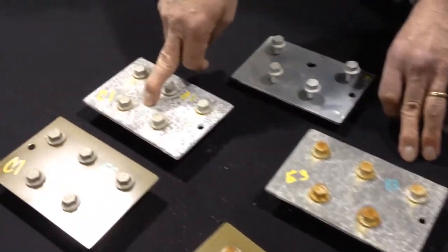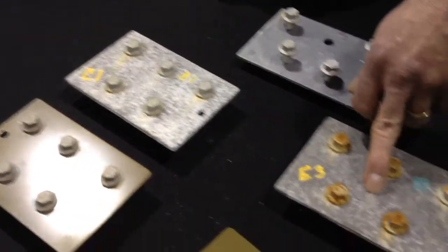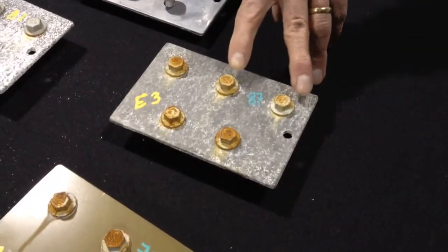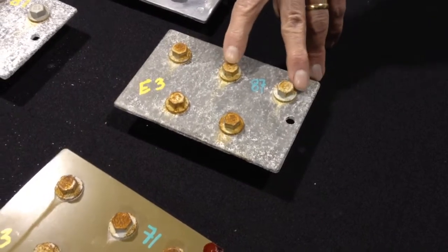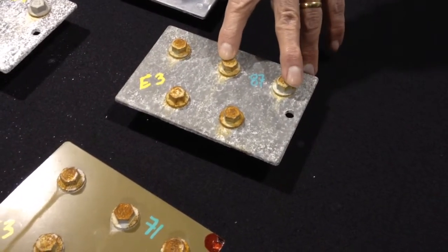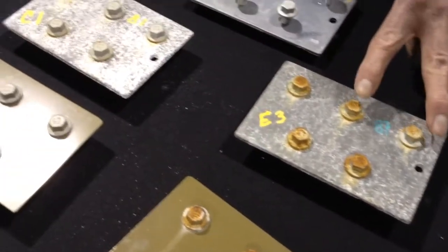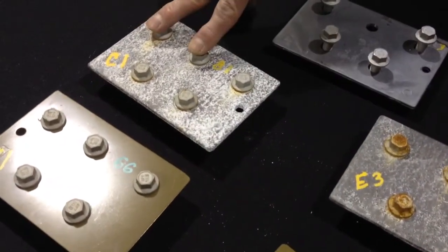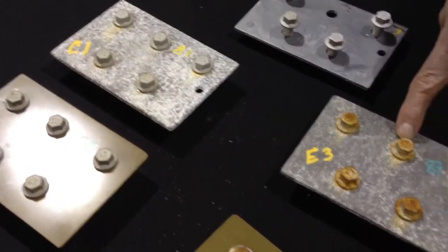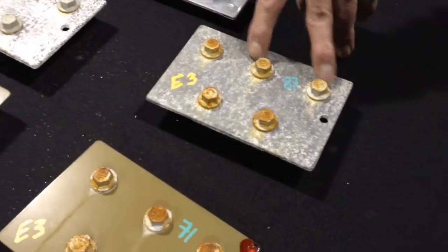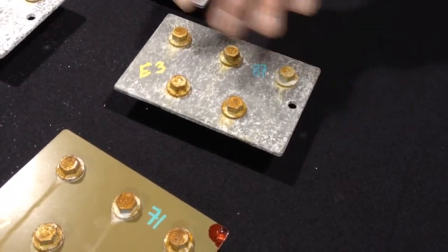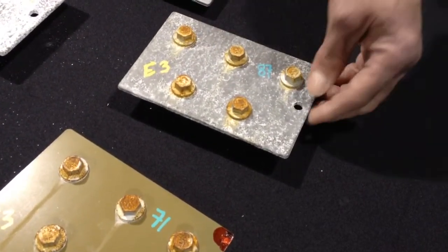This one completed our testing. This one went less than halfway through our testing. You can see that the finish, the coating that we put on the fasteners for this panel was much worse, much less robust than this coating. It allowed the fasteners to start rusting, so now we have some bare steel that's available to start touching the aluminum and corroding.